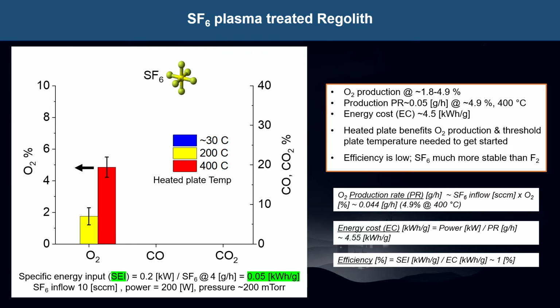We've analyzed 3 gases. There's no carbon source in there, so we're not seeing any carbon production or CO or CO2 production. We're only seeing oxygen production. And we've varied the heated plate temperature. So 30 degrees here represents ambient, no heated plate on. 200 and 400 are set points for the heated plate. So indeed, we do need some kind of heating on the plate to get the reaction going. But once it's going, we're getting somewhere around 2 to 5% of the exhaust mix that has oxygen in it. This is a production rate which is quite small given the flows of about 50 milligrams per hour.